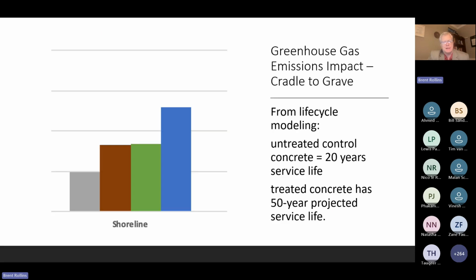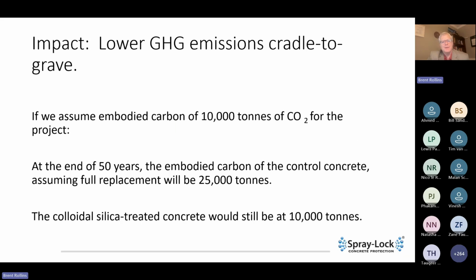So what that means is the impact on total life cycle of the structure and greenhouse gas emissions. You get an untreated control concrete with 20 years of service life. Treated concrete has a 50-year projected service life. What that turns into is, if we assume 10,000 tons, just for a round number, of CO2 equivalent embodiment for the project, at the end of 50 years the embodied carbon of the control concrete, assuming full replacement, would be 25,000 tons if we didn't treat it with colloidal silica.